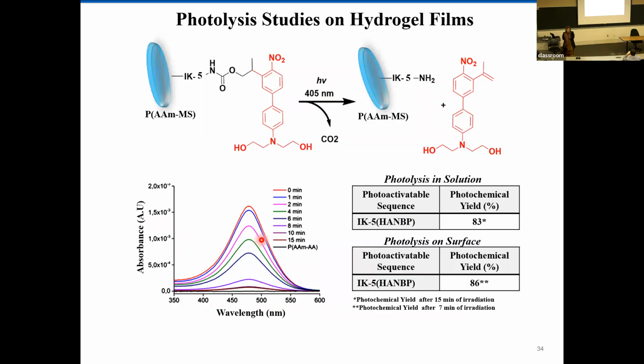So now we have our peptide, we have the caged version, and we have the hydrogel. Before putting cells on top, we want to make sure that we can do the uncaging. We can do the uncaging in solution using a 405 nanometer laser. The longer you shine the light, the more photocages get removed, and we can have 83% removal of this caging group in 15 minutes.